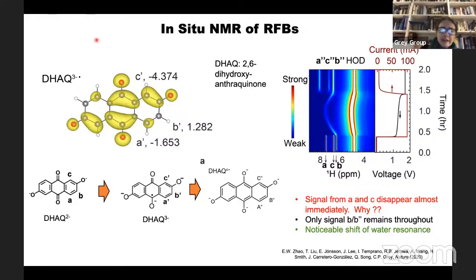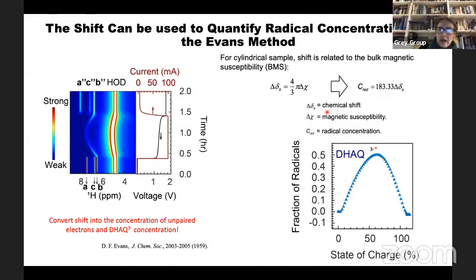We do DFT to look at where the electrons are, and you can pull out the hyperfine coupling constant, the coupling between the protons and the unpaired electrons, which is what's shown here. You can see from an electron density map that there's not very much electron density on the B protons, and that's why you can still see it. So that makes sense.